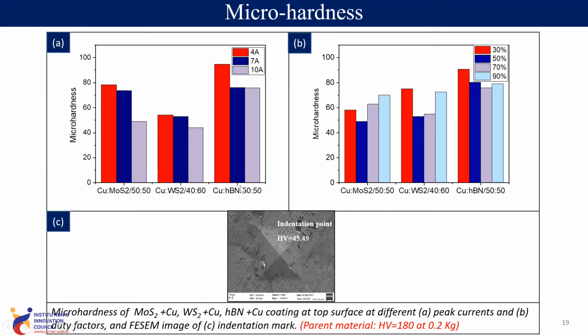So this is the indentation point as proof that we have obtained the low hardness, that is actually 45.49. That's the indentation point, captured in the micro hardness machine at 0.2 kg load.